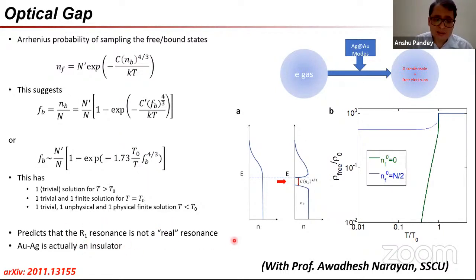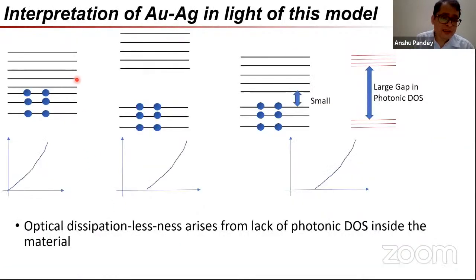And furthermore, it makes a very interesting prediction, which is very comforting to me, which is that this R1 resonance, as we initially have been calling it, is not a real resonance. What I mean by that is this. In the conventional picture, we would be worried that we are introducing a gap in the density of states. Within this model, this gap in the density of states can be quite small. Rather, what needs to be large is the gap in the photonic density of states. It is being produced simply because the cavity mode is shifting all the other electromagnetic modes away from it. There's a reduced density of photonic states.